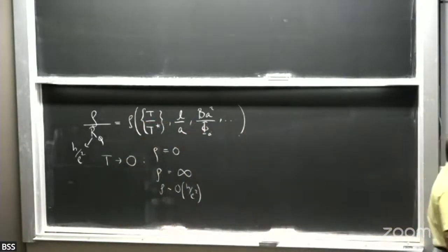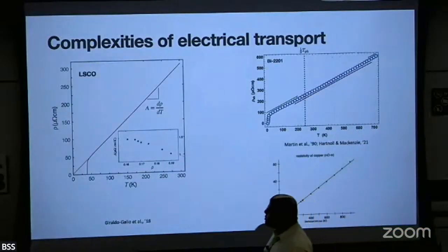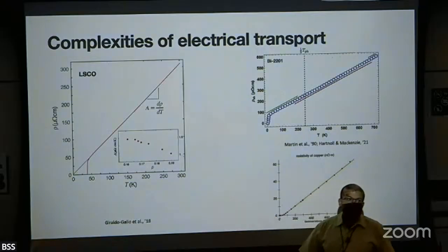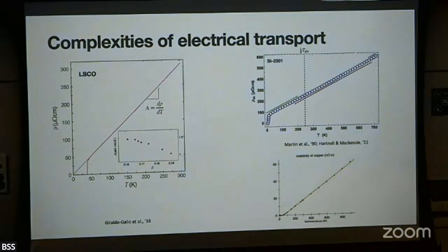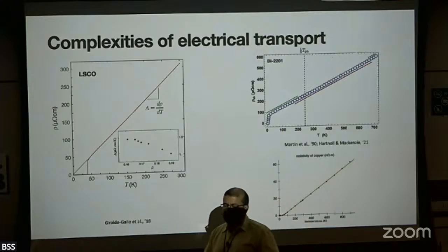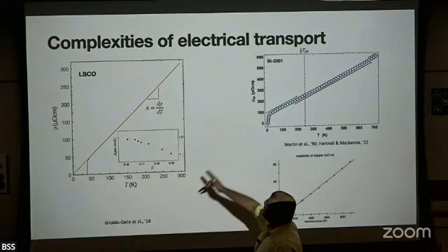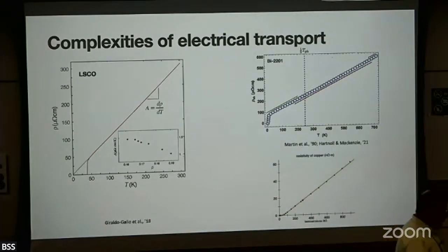So why do we care about this messy thing? Well, because it turns out there are a lot of compounds where something truly miraculous happens. Again, this is what people have been obsessed with. So this is data on one particular hole-doped cuprate, near optimal doping, LSCO. This is actually very old data from the 90s in a different cuprate. And it's not as if hole-doped cuprates universally across doping regimes show this behavior. There are certain points in parameter space where this occurs, but you see this and you notice that starting from a very low temperature scale up to very high temperature scales, quite often up to a point at which the crystal melts, you see this very nice T-linear resistivity.